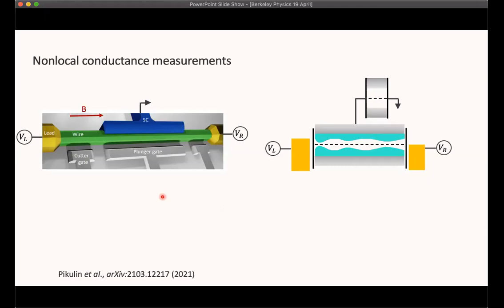We can choose to do non-local conductance measurements. So this is a new technique that's been developed in the last couple of years, but it's relatively simple. Instead of modulating the voltage on one junction and measuring the current that results, we can modulate the voltage on one side of a two-junction device and measure the current on the other side and vice versa. And now what's interesting about doing this is that if you modulate the voltage on the left side, say, and measure the current on the right side, then you only expect current to flow through the lowest continuous energy state that spans the entire wire. Now, this is making a couple assumptions about a lack of relaxation, but it's a useful and mostly true assumption to make.